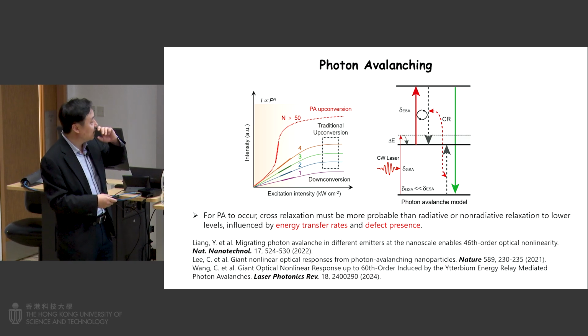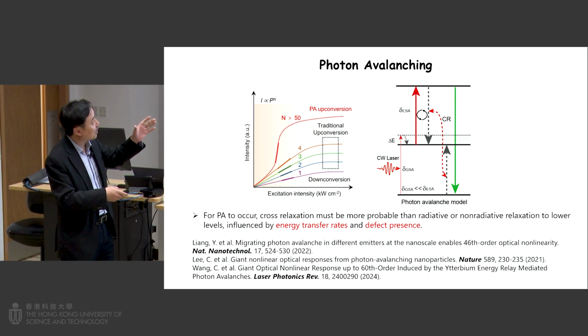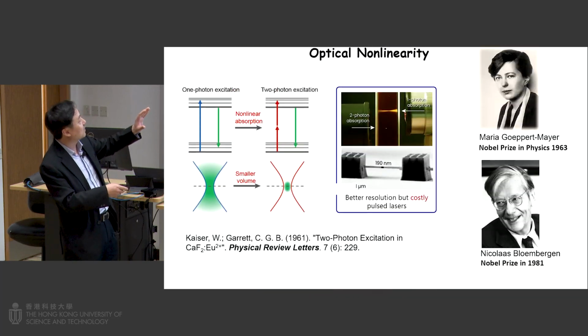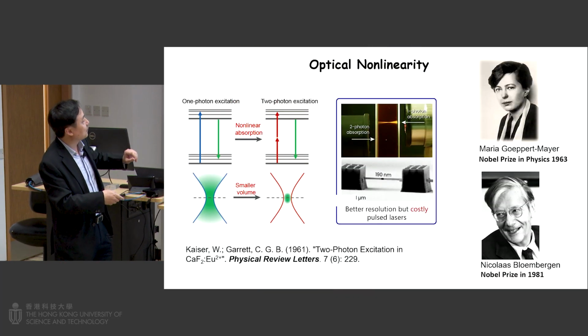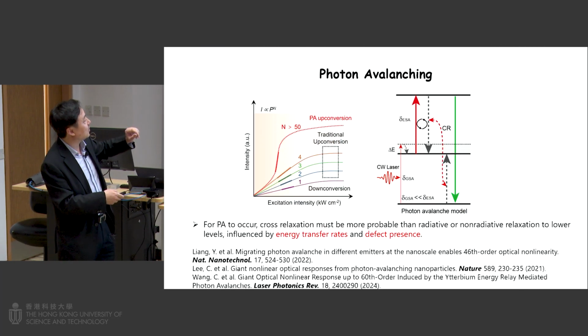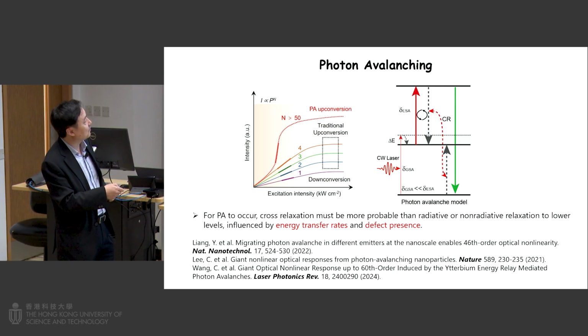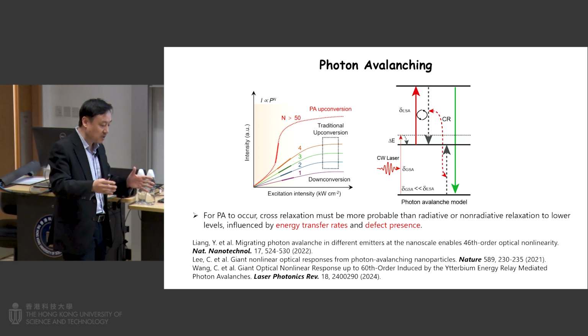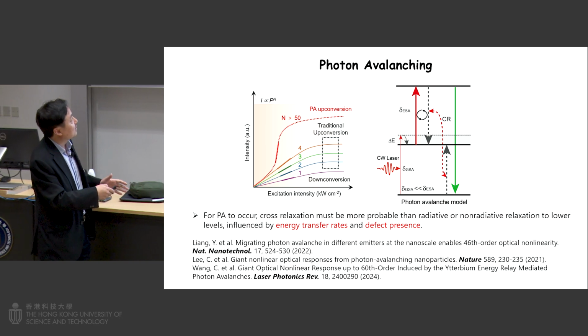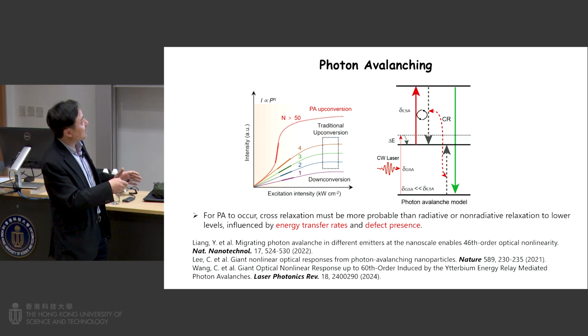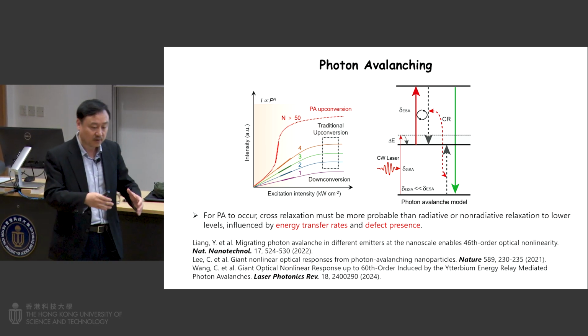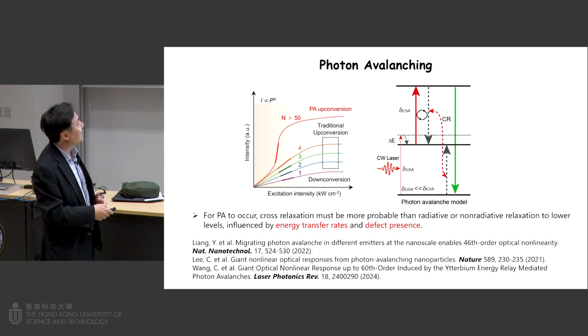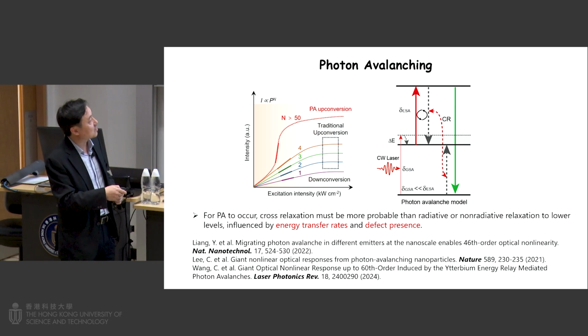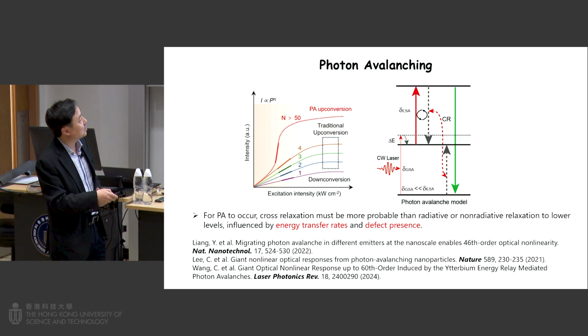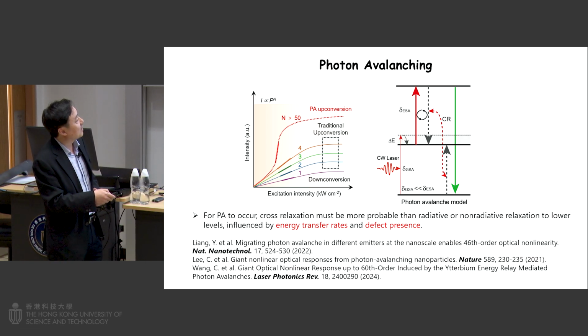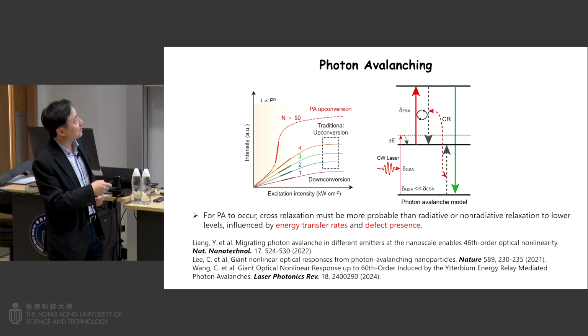So photon avalanche is quite interesting. Why do I mention this? Because if you look at the nonlinearity of two-photon excitation, you can extend it to three-photon, four-photon. You can play with the optical setup and achieve a nonlinearity index of maybe around 4. That's already the ultimate limit. But using these lanthanide-doped particles, it was reported you can achieve very high nonlinearity, around 40, 50.